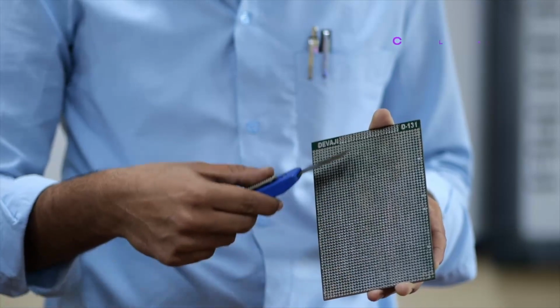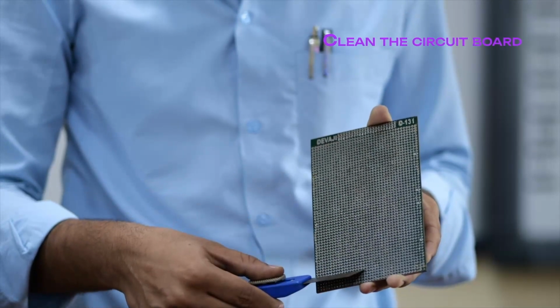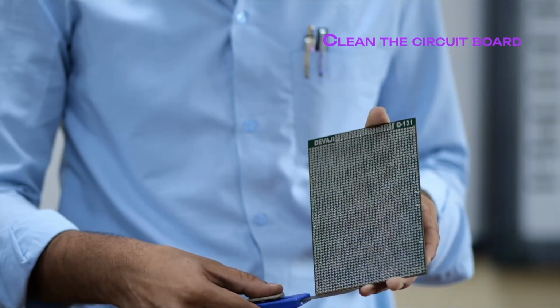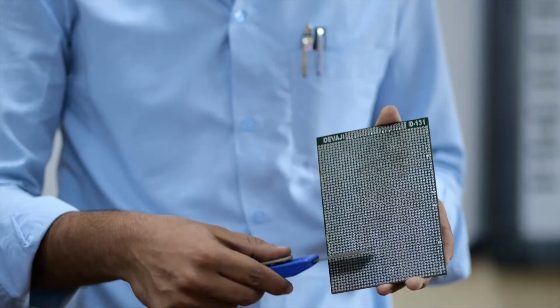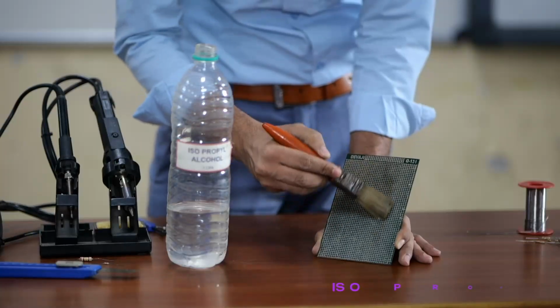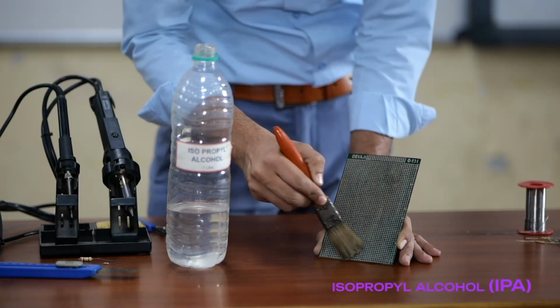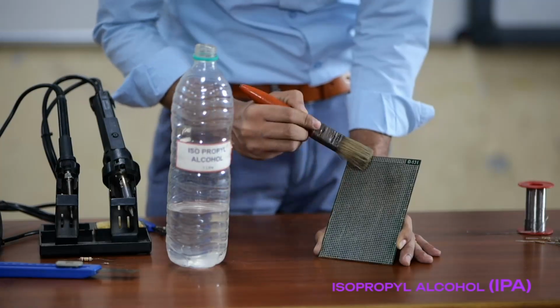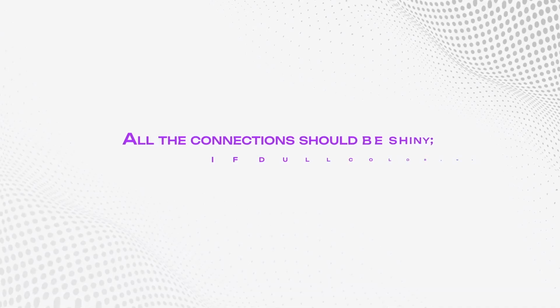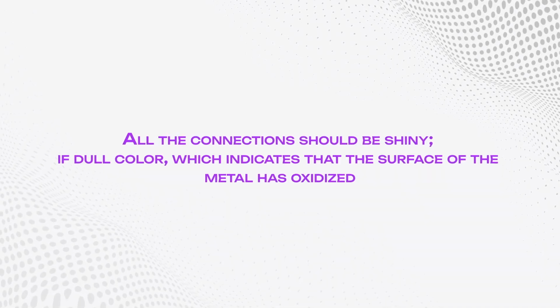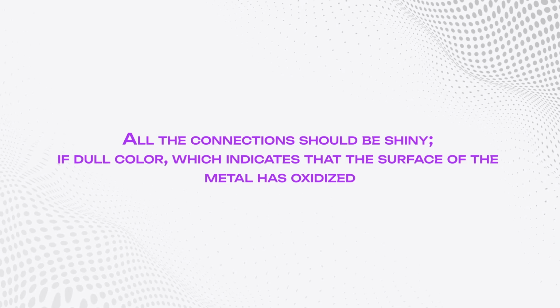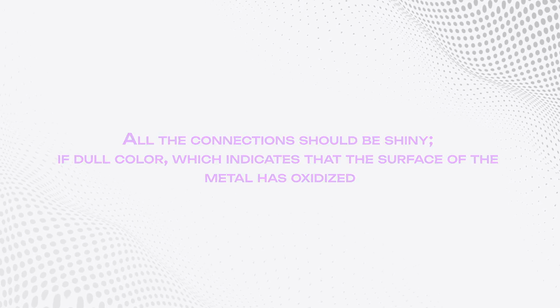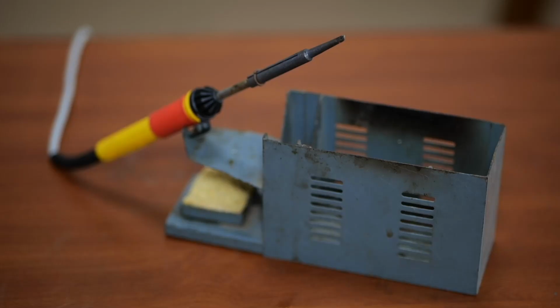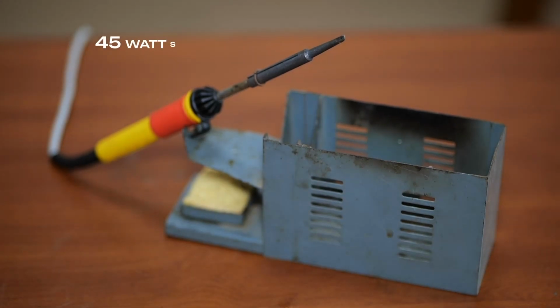Clean the circuit board to remove any oxidation or grease from the solder pads, which can repel molten solder and cause beading. Use a cleaning agent such as isopropyl alcohol, small brush, or cotton cloth for cleaning the board. All the connections should be shiny; a dull color indicates that the surface of the metal has oxidized. Select the appropriate bit for the soldering iron, which is suitable for PCB soldering, and choose the wattage of the soldering iron not more than 45 watts.